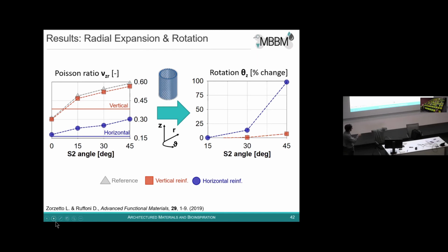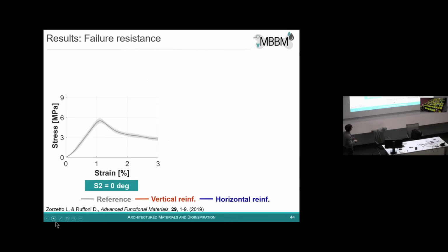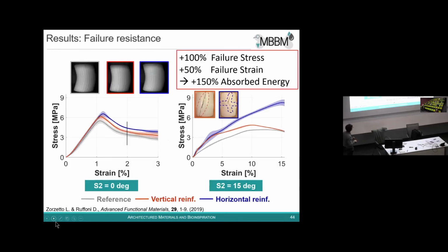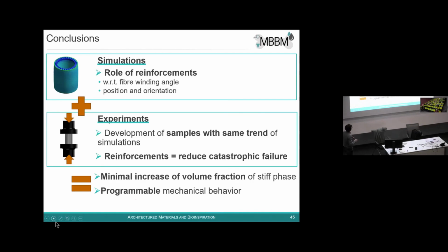And on the other side, what is increasing is the rotation of the cylinder. So the rotation along the vertical axis is increased where we add horizontal reinforcement. So the horizontal reinforcement is actually triggering more rotation of the system, and this is something that is delaying the failure and also deviating the crack from vertical to horizontal direction. So I think this is something that we showed.